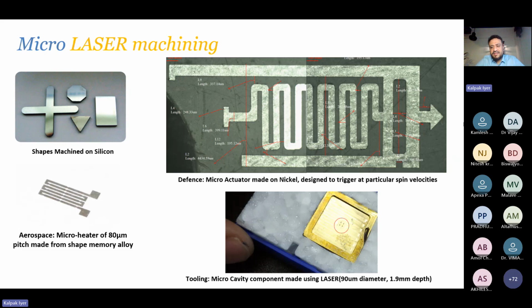A lot of the other processes are slow, very intensive, but this is very good for 2D machining or making some holes. Here on the right top, you can see a part that was a trial we were doing with DRDO of a spin actuator for triggering missile systems. This is a micro heater made out of nitinol or shape memory alloy for an aerospace application. These are just some silicon blocks that we machined, and some micro cavities for the micro needles were machined using micro laser machining.